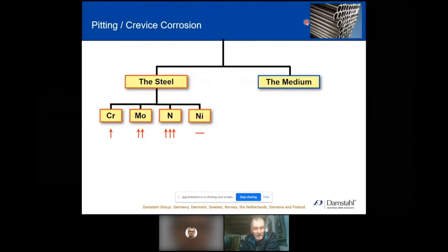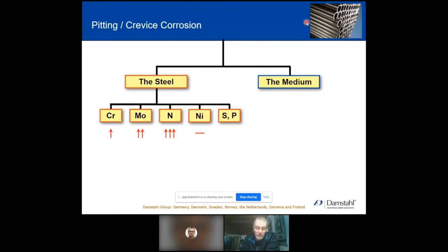Finally, the number of impurities: sulfur, phosphorus, could be carbon, could be selenium, silicon. The higher the amount of impurities, the worse, because these ones work as attack points. And we want to avoid these ones. We want to avoid weak parts of the fishing line. These three are normally the ones we focus on the most when you're talking about the positive side.